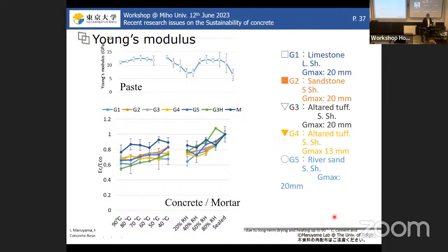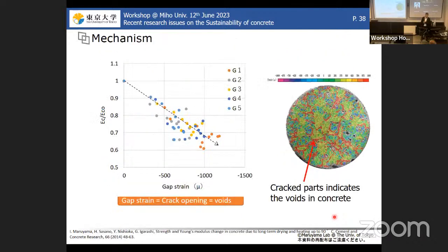Even at 60%, we see maybe at most a 30% reduction of the Young modulus due to drying. And if we try to evaluate this reduction of the Young modulus considering the crack opening inside, this can be evaluated by the gap strain between the concrete strain and the mortar strain at the same drying state. So this difference should be compensated by a crack opening inside.